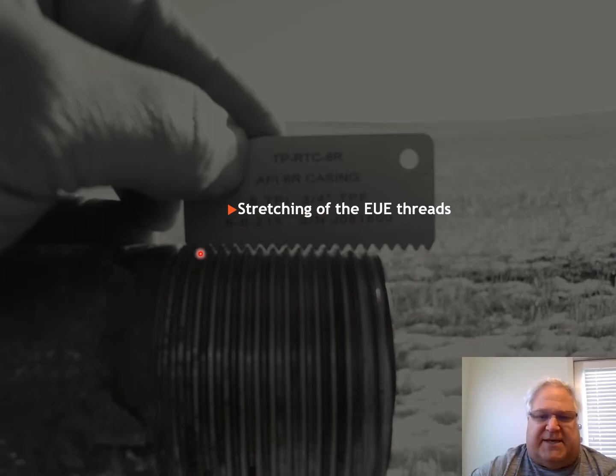Again, here's another example. You can see basically right here in this area, if you look at how it's lined up, and then right here, there's interference between the gauge and the threads, and that's where it's stretching. So this is probably where that thread was last engaged into the wellhead, and it's stretched right at this point.